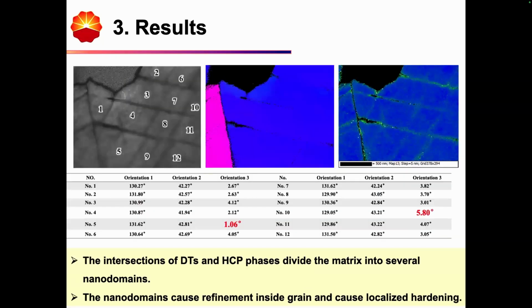As we can see, there is a series of nanodomains inside one grain. Therefore we apply some TKD analysis. First, we can see that along these nanodomain lines, there are some strain concentrations based on the KAM analysis. We have also looked at the orientation transformations around different TKD analyses.